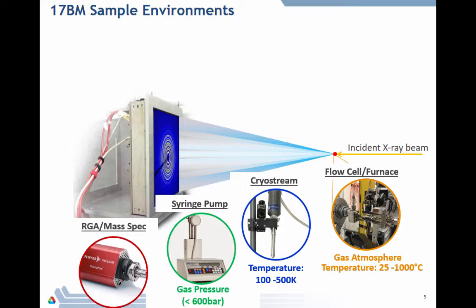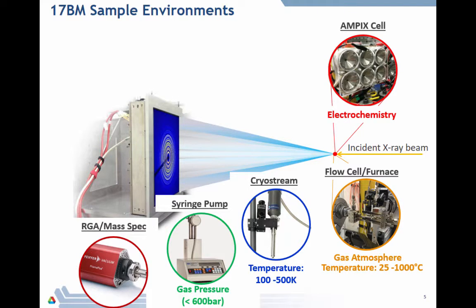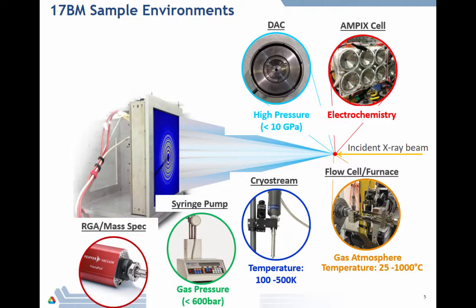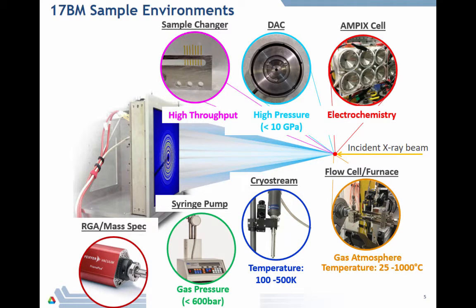We perform experiments at our beamline studying different electrochemical systems with an AMPIX cell. If you're interested in high pressure measurements, in terms of diamond anvil cell high pressures, we have that. Our diamond anvil cell can go up to 10 GPa. And again, since we can collect data rapidly, if you don't want to collect so much data from just one sample, you can imagine you can do high throughput measurements and collect lots of data from different samples. So we do have access to the sample changer and collect multiple samples very rapidly.